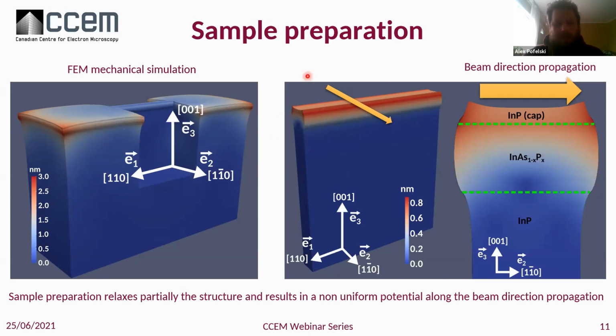This is representing the displacement. This is a displacement map, which simplifies the problem, since we have only some displacement, some deformation going either along the 110 direction, which is the direction of the beam propagation, the lamellar thickness, and along the growth direction. So we can simplify this 3D geometry to this system. Here we have an exaggeration of the deformation that is happening, and you can see the edges are bowed. And then we will have the beam crossing this 3D geometry. So sample preparation relaxes the structure partially, so we still have some strain inside.